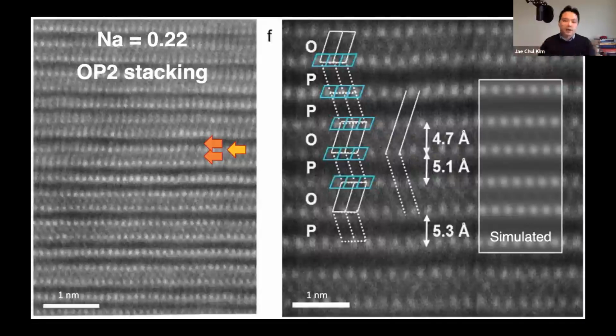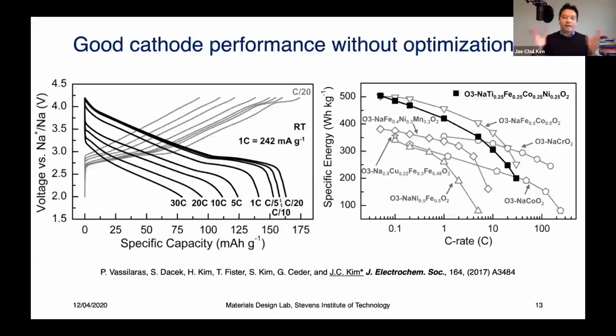So I am particularly proud of this result. This is sort of the first observation of alternating octahedral and prismatic sites in an OP2 type setting. This alphanumeric definition describes how the oxygen layer stacking repeats. Long story short, this is a very interesting result to see how a sodium battery phase transforms at high state of charge.